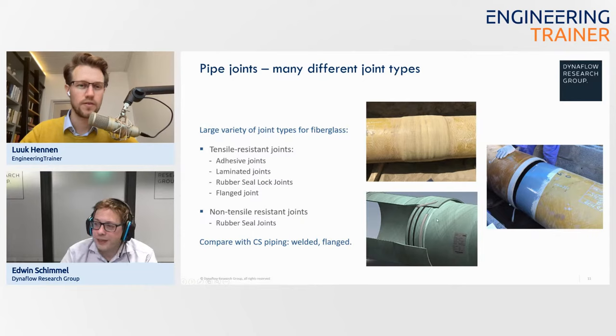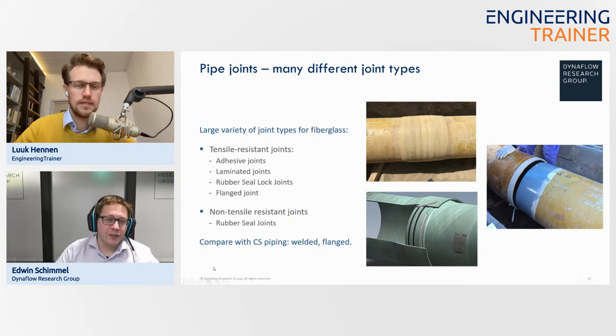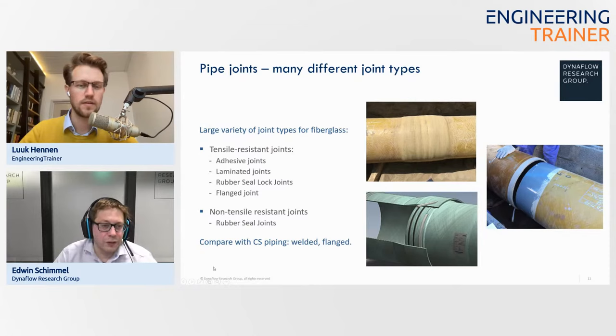So often, close to an elbow, the first one or two joints are laminated joints, and after that you see the locking ring. And also, if you have a large diameter change, so you have a large reducer here, and then immediately after that the locking ring, then the reducer also puts a lot of pressure thrust on your piping and locking ring. So also there I would be careful. So these joints with locking rings, you preferably have them not at locations where you put the full pressure thrust on it. If you want to do so, then the qualification program could cover it, but if not fully qualified, then stay away from locations with a lot of pressure thrust.